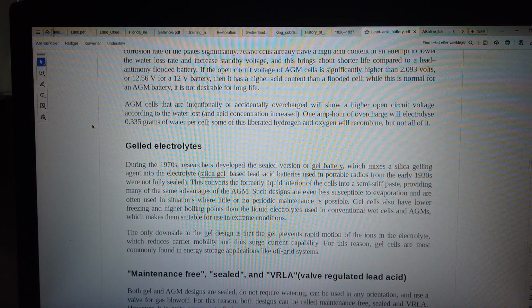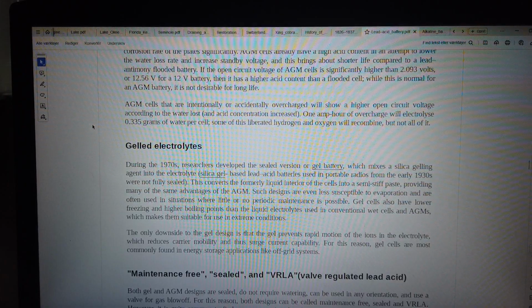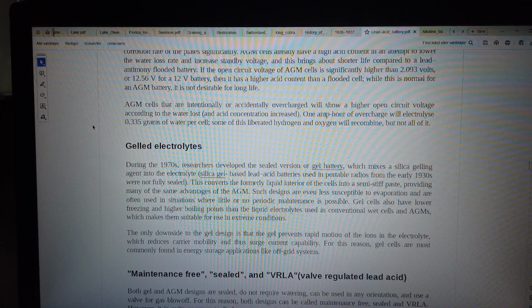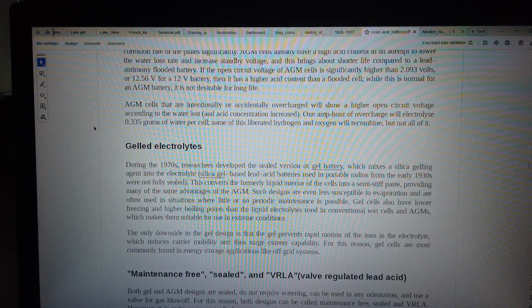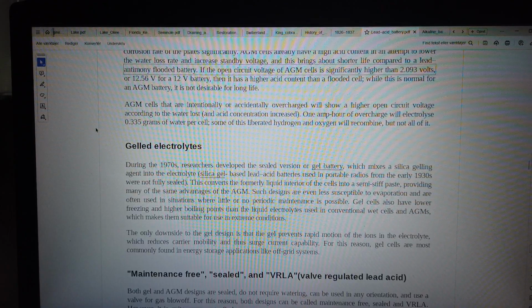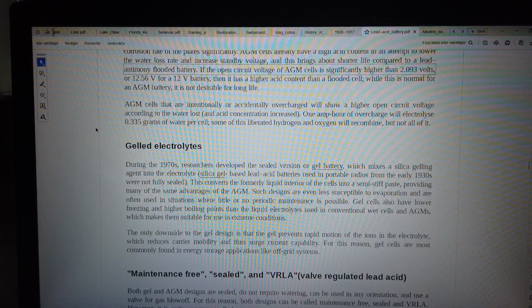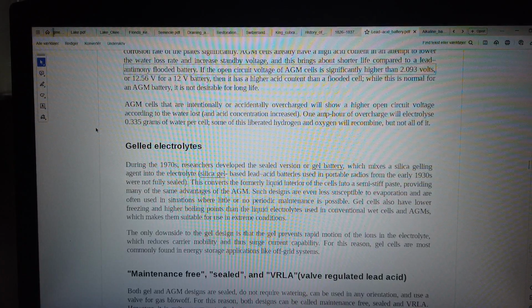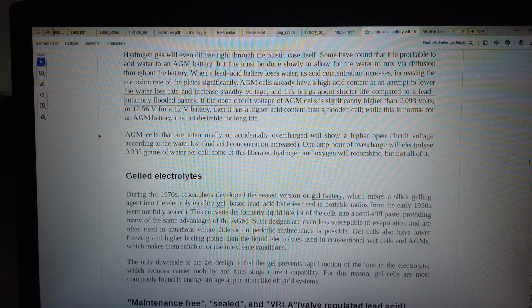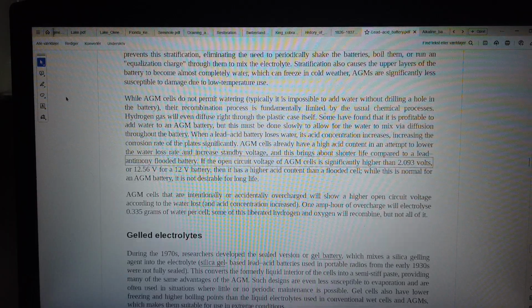AGM cells that are intentionally or accidentally overcharged will show a higher open circuit voltage according to the water lost, and acid concentration increased. 1 amp-hour of overcharge will electrolyze 0.335 grams of water per cell, some of this liberated as gas. If the open circuit voltage of AGM cells is significantly higher than 2.093 volts,